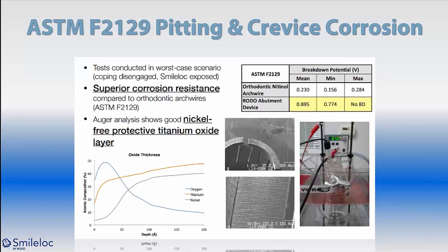In an ASTM F2129 pitting and crevice corrosion test, the test was conducted in a worst-case scenario. In other words, where the coping disengaged and the Smileloc was exposed to the oral cavity. What they found was superior corrosion resistance compared to orthodontic arch wires. The Auger analysis shows that there was good nickel-free protective titanium oxide layers around the Smileloc, resulting in no nickel leaching into our systems.